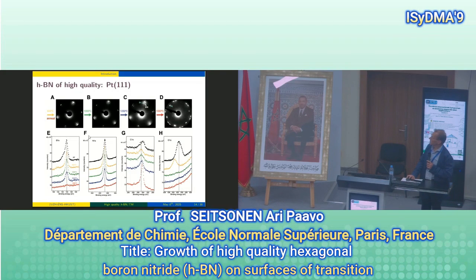And initially there's of course boron, nitrogen. They were the elements that were grown on the surface, but then there appears also some carbon. And as a function of the temperature, first you see that the boron is disappearing from the surface because the signal, the magnitude at this energy, disappears. Then the nitrogen starts to disappear. But the signal of carbon remains strong, and it even increases. And the oxygen, there's some oxygen initially, some impurity probably, but it disappears also at reasonably low annealing temperatures. So first oxygen disappears, then boron, nitrogen, but the carbon stays until the highest annealing temperature. So here it's 1080 degrees Celsius.